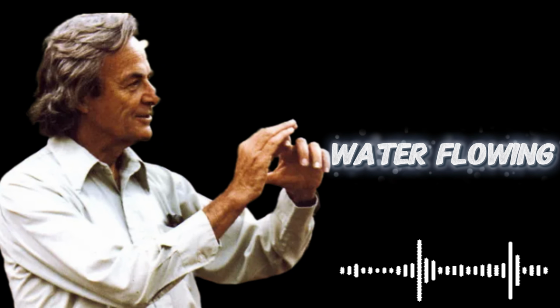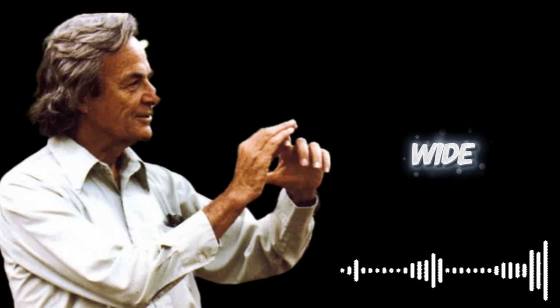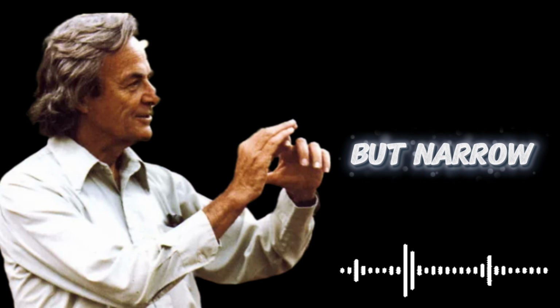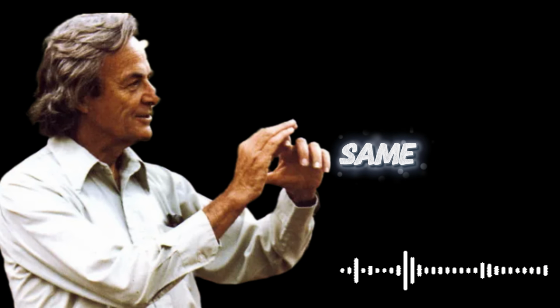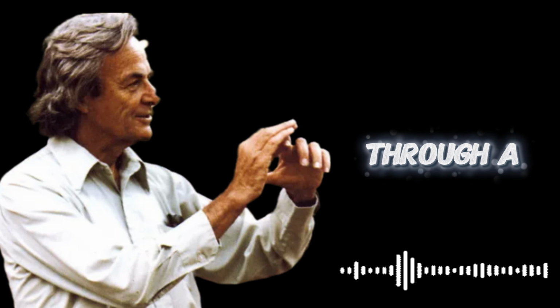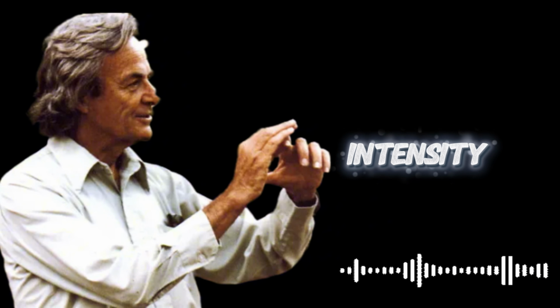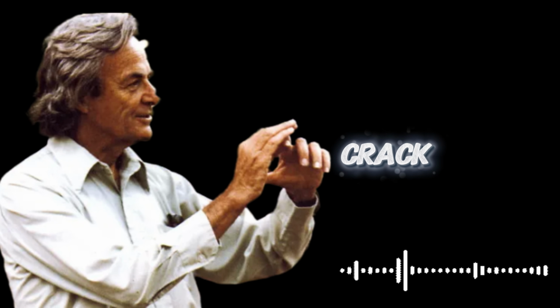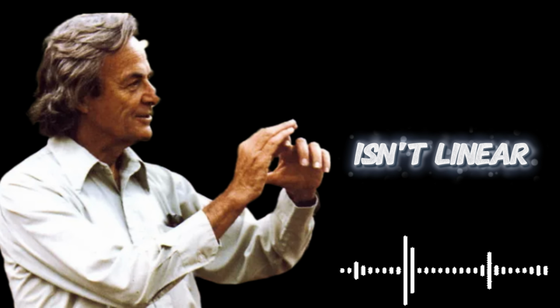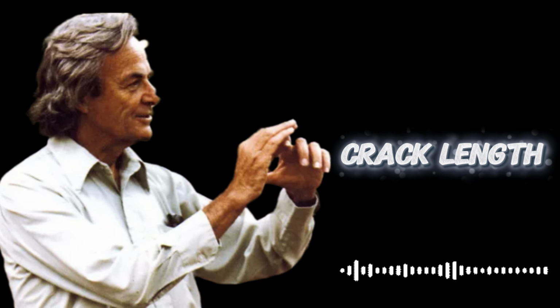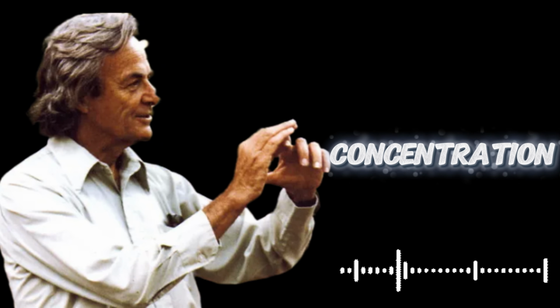It's like water flowing in a river. When the river is wide, the water flows gently. But narrow the river, and the same amount of water has to flow faster through a smaller space. The crack tip is like that narrowing. The stress intensity at the crack tip depends on the applied stress, yes, but also on the crack length. And here's the killer. The stress concentration factor isn't linear with crack length. It goes with the square root of the crack length. A crack that's 4 times longer creates twice the stress concentration.